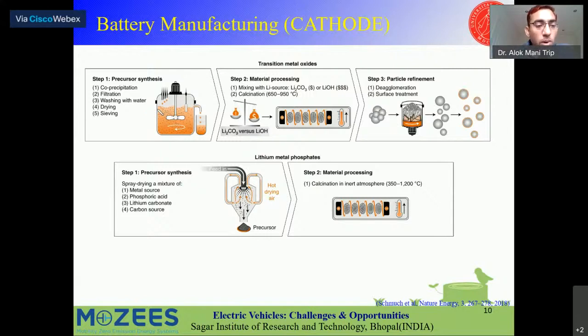So the co-precipitation method is a commonly used industrial method to make cathode material. They take the precursor, precipitate, and then calcine it. After calcination, they remove the impurities, meaning the other products, and then finally they get the desired particle, and then they are tuning something in the chemistry. I'm not going into that. They are modifying it so that they can tune the particle size, because this also affects the diffusivity and lots of kinetic parameters. Even the internal cell resistance is affected by the particle size. So these are very important things, and they are doing lots of modifications to get a better particle size. Sometimes they are doing surface modifications also, like some kind of metallic coatings.